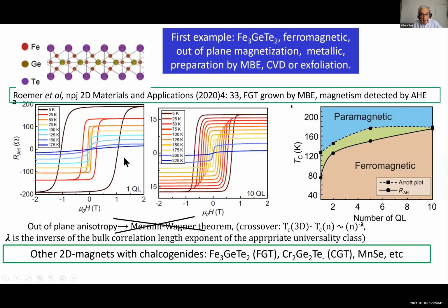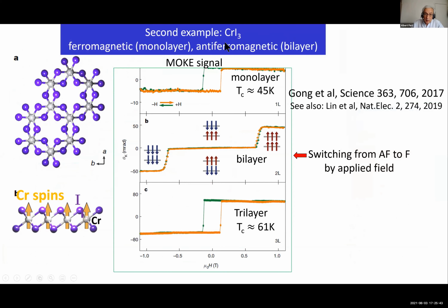From the analysis of this curve and from the classical Arrott plot, you can see the ordering temperature as a function of the number of layers. I don't want to explain the theory of this ordering. Simply, I have said that you can escape from the Mermin-Wagner theorem by introducing some anisotropy and even more by introducing some coupling between different layers. And, for example, you can explain how the ordering temperature increases with the number of layers in this FGT system. But I don't want to develop these questions. So this is a good example of a ferromagnetic 2D material. And another classical material also is CrI3, chromium iodide.